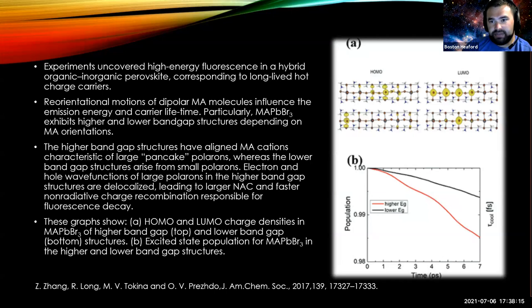And so some other experiments that were conducted showed that there was some high energy fluorescence in hybrid organic inorganic perovskites, which corresponds to long-lived hot charge carriers, which is, again, a good thing. You want long-lived charge carriers. And they suspected that reorientational motions of the dipolar methylammonium molecules influence the emission energy and carrier lifetime, particularly the methylammonium lead bromide exhibits higher and lower band gap structures depending on the methylammonium orientations.